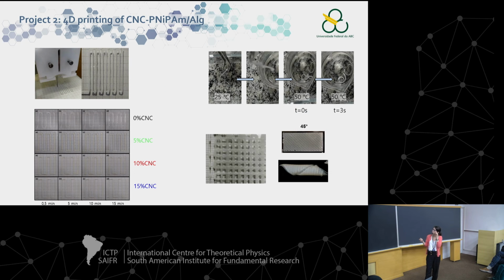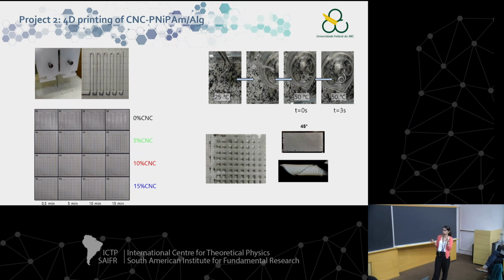So after that, we optimize the printing parameters. We check the shape fidelity for all these compositions, and we saw that the 10% CNC is the best. We confirm that we have temperature responsiveness: at low temperature we have this extended filament, and at high temperature, very quickly, this filament shrinks and folds. And we check that, depending on the angle between two deposited layers, we can have twisting of our printed shapes.